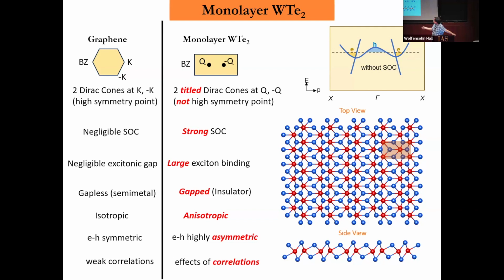Graphene is gapless, we know that. This material, because of strong SOC and excitonic binding energy, becomes gapped. So it's an insulator in its intrinsic form in the monolayer case.